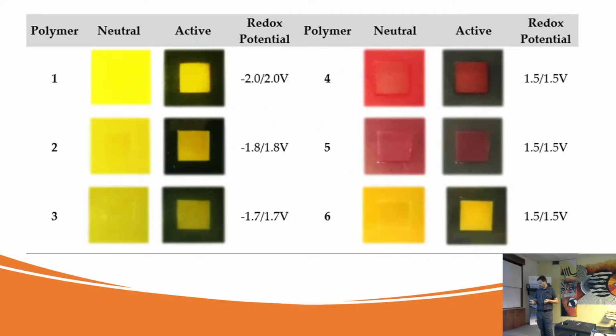And here it is, the polymers, different polymers. So these polymers also produce the yellow color. The problem is that you have to apply potentials that are too high for a device, because then it starts to react with the ITO that you have there. But with this polymer 6, we indeed produce the yellow color.